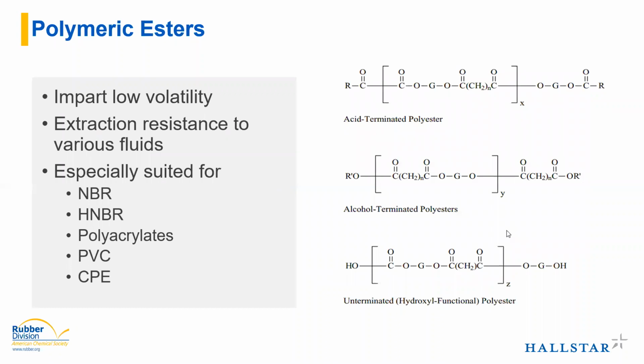Polymeric esters, on the other hand, give very low volatility because they are such large molecules in comparison to the monomeric esters. They have excellent extraction resistance to a wide variety of fluids because they are so large. They don't move as freely. And these are especially suited for higher performing applications and elastomers. So similar to the monomerics, but also things like HNBR, polyacrylates, just the higher performing materials.